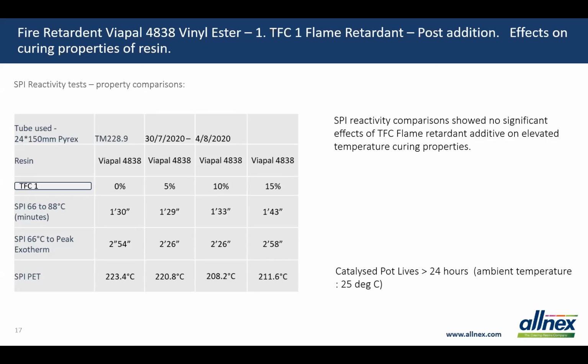SPI reactivity tests are common for characterizing pultrusion systems for reactivity and assessing how they'll run on the line. In this case, this type of flame retardant can often inhibit the curing rate of the vinyl ester and polyester resins. However, this particular material doesn't show any significant negative effects on curing at all, as can be seen in these results. And also the catalyzed pot life appears to be largely unaffected. So it's quite inert in terms of not affecting the cure, which is positive.